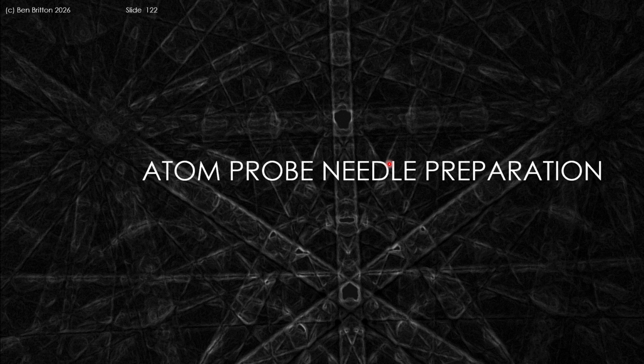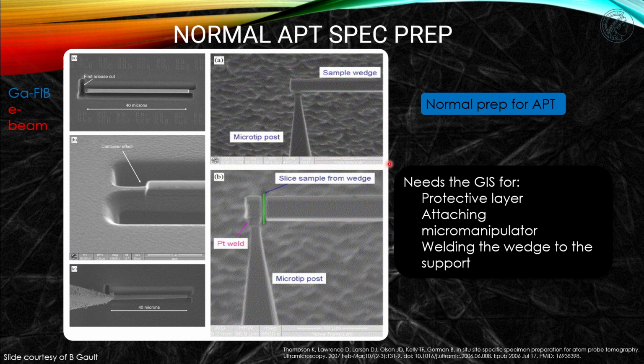Moving beyond TEM lamella prep, we can also use atom probe tomography. For those of you unfamiliar, there are many other sources for how APT works, but broadly speaking, we produce a sharp needle and we evaporate the surface atoms as ions in a controlled manner in a very expensive but very useful atom probe tomography instrument. One of the growths of this area is to use this to do site-specific work, but in addition to site-specific work, you can also do things like look at insulator samples that can be difficult to prepare using other methods.